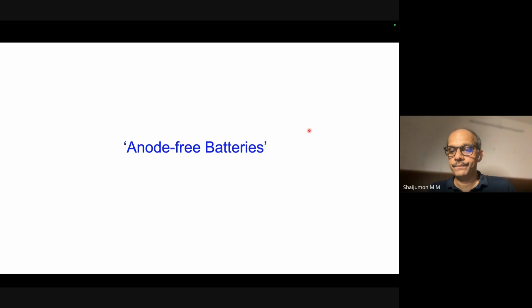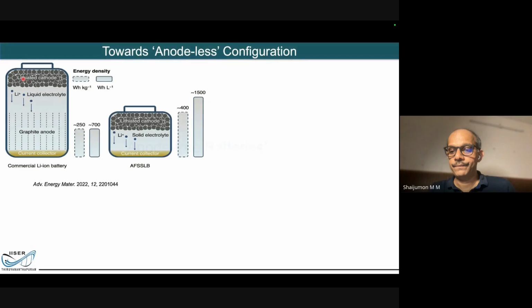There is another interesting concept which has recently come up, which is called anode-free batteries. For any battery, you have to have a cathode, the black one that you see here. You have to have an anode, which is the typical graphite. And of course, there is a current collector, which is copper at the anode side and aluminum at the cathode side. That's a typical architecture for a traditional battery, which leaves us with a gravimetric energy density of about 250 watt-hour per kilogram.